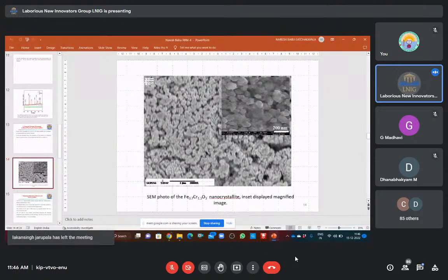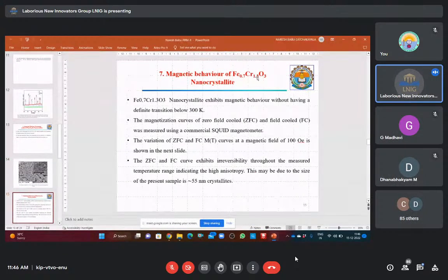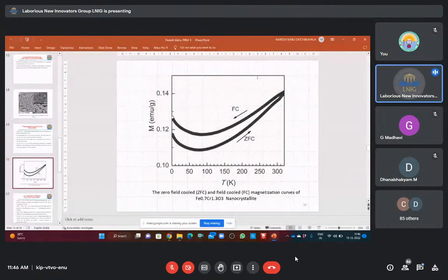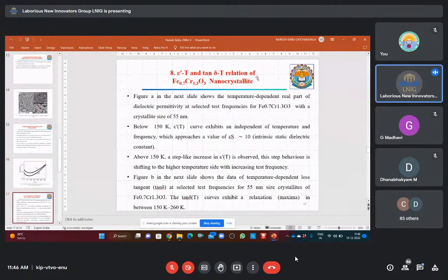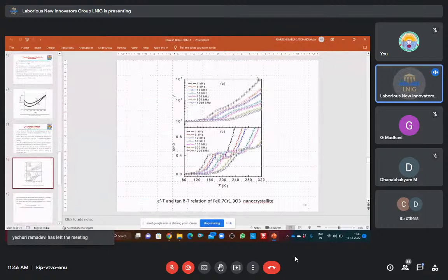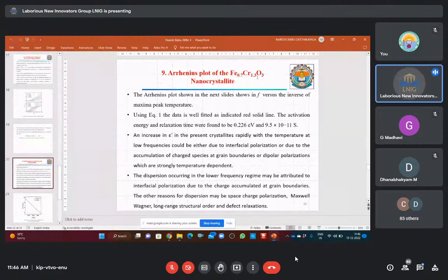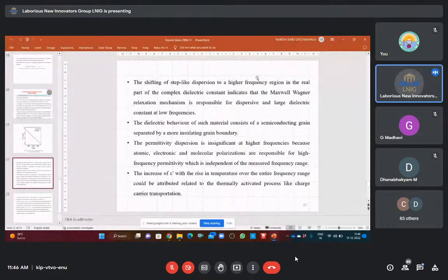And these are the studies of scanning electron microscopy of that nanocrystallite. And this is the image, the SEM photo of that particular nanocrystallite. And this slide shows the magnetic behavior of the iron chromium doped nanocrystallite. This is the zero field cooled and field cooled magnetization curve. And these slides show the temperature behavior, how the temperature varies, which can be discussed using these graphs also. This is the Arrhenius plot of the nanocrystallites.